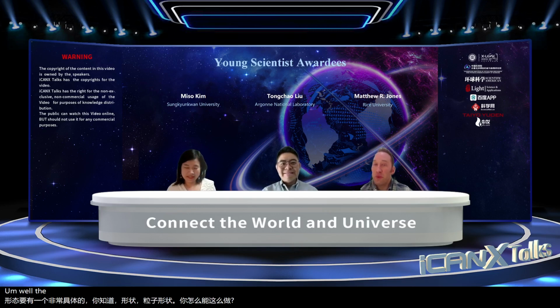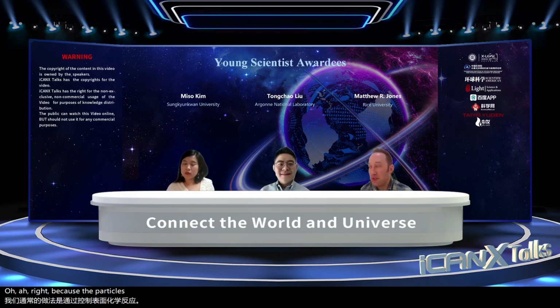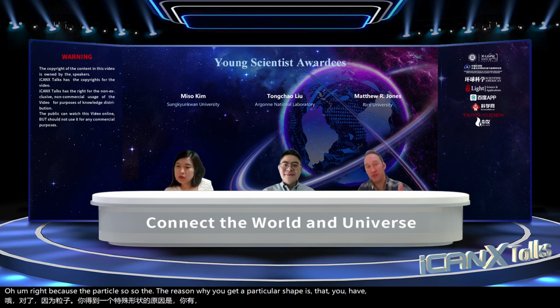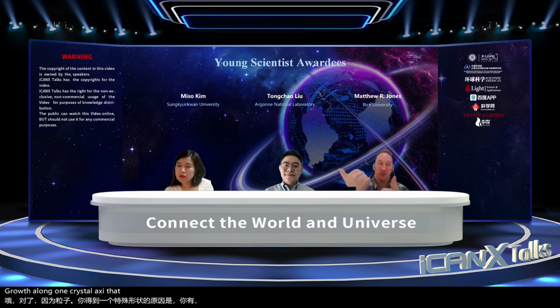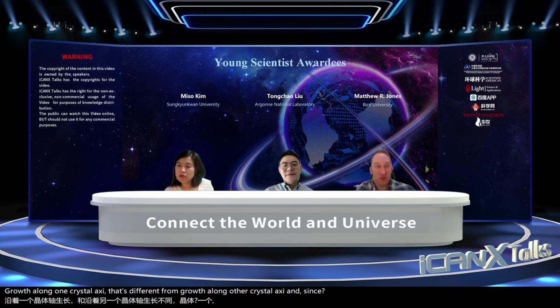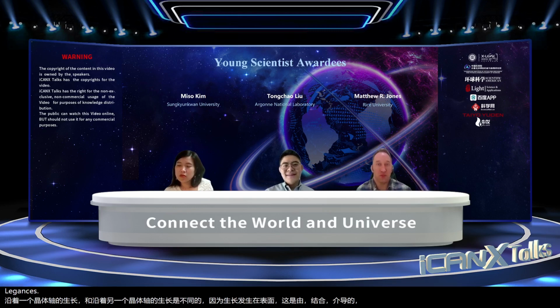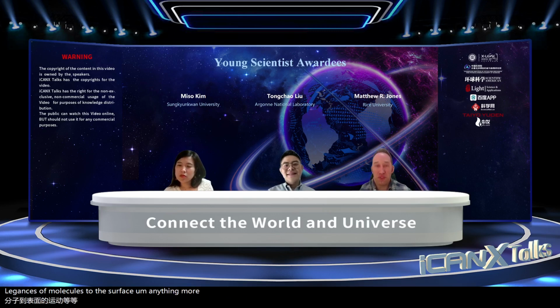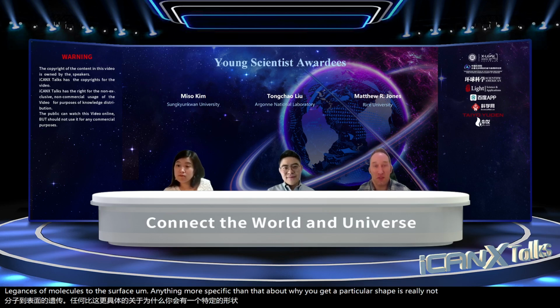Well, the way we do it normally is by controlling the surface chemistry. The reason you get a particular shape is that you have growth along one crystal axis that's different from growth along another crystal axis. And since growth is occurring at the surface, that's mediated by the binding of ligands, of molecules to the surface. Anything more specific than that about why you get a particular shape is really not well known at all.